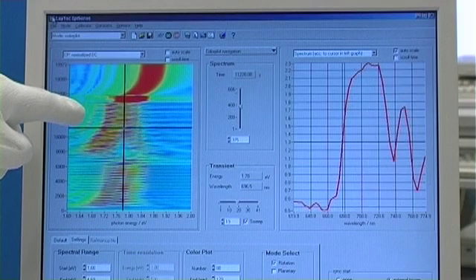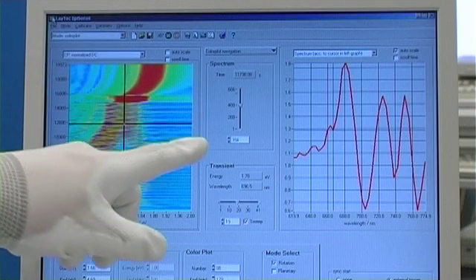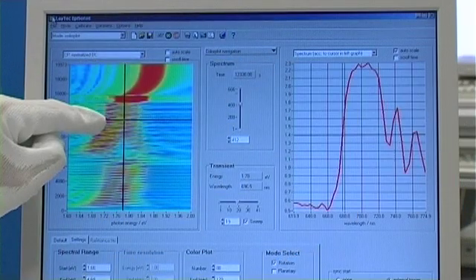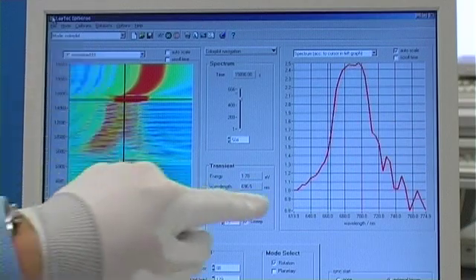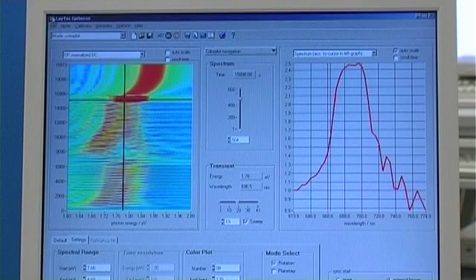And when we go through all these layers, you'll see every layer has a different spectral shape. And when we wanted to have a laser structure emitting around 690 nanometers, so when we go to the last layer here, you can see that we have exactly matched our laser measurements around 690 nanometers. And from this you can see that this EPI-RAS sensor helps us very much to control and adjust our growth process for the desired wavelengths.